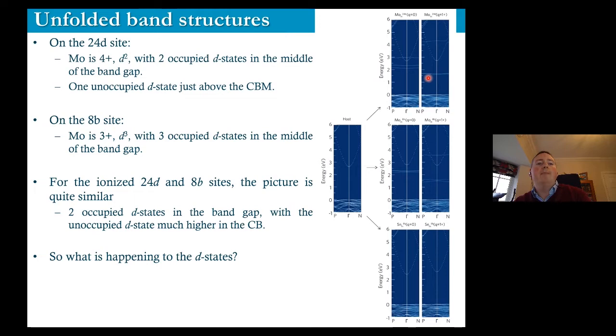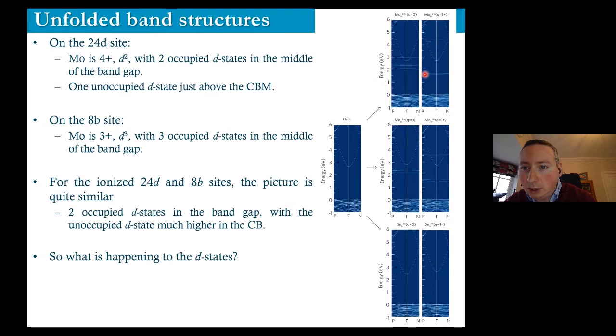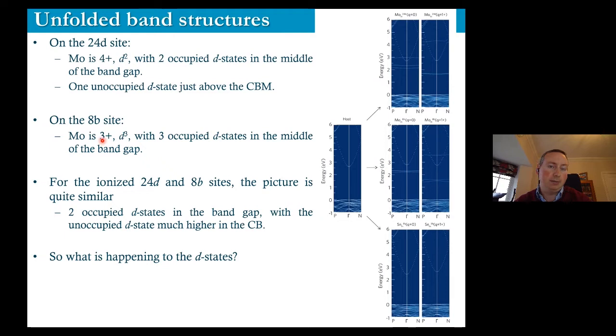To understand what molybdenum does when incorporated into the indium oxide matrix, we unfolded the band structures from supercells back onto the primitive cell band structure. When we place molybdenum onto the 24d site, molybdenum is 4+ — a formally D2 cation — with two occupied D states in the middle of the band gap and one unoccupied D state just above the conduction band minimum. When you ionise that defect, the two occupied D states are stabilised downwards in energy, and the unoccupied D state is destabilised upwards in energy. For the 8b site, you end up with three occupied D states in the middle of the band gap, making it formally molybdenum 3+, but when ionised you get a similar picture: two states stabilised and one state destabilised.